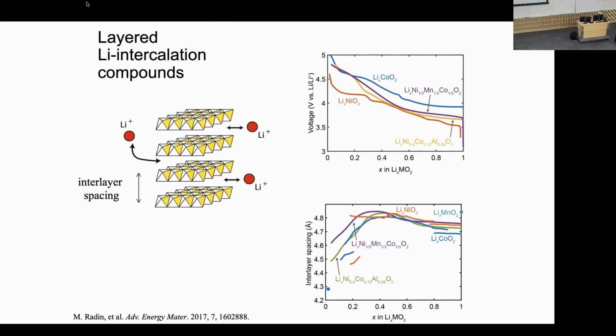This is again the layered material, but now looking at the voltage curve for a variety of different chemistries. So these all adopt the same crystal structure. All we're doing is just taking these sites, these transition metal sites, and alloying them either with cobalt, nickel, or a mixture of them. And you can see each of these, when you change the transition metal, their voltages all change. And that means the transition metal is affecting the types of phase transitions that occur when you insert and remove lithium ions. So you get kinks and plateaus at different compositions.